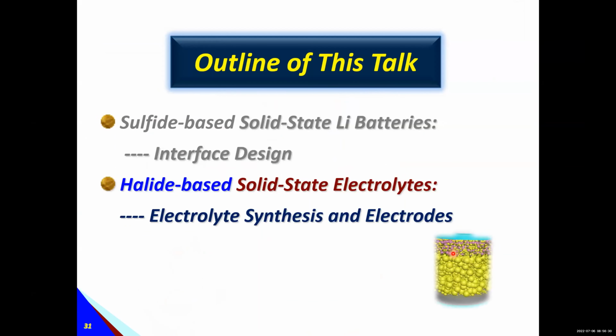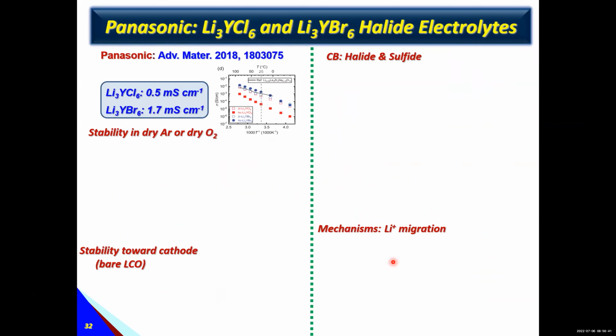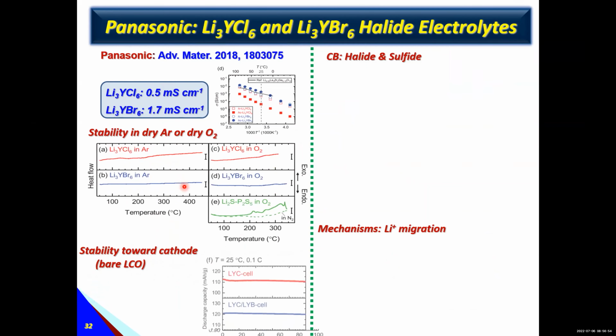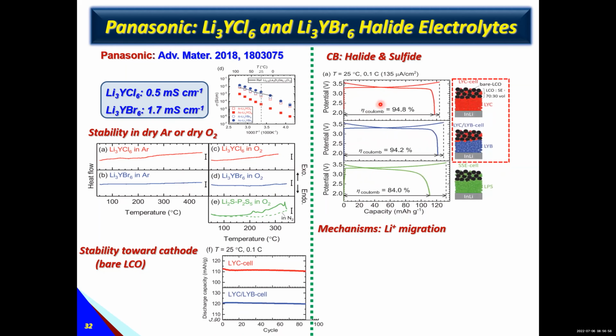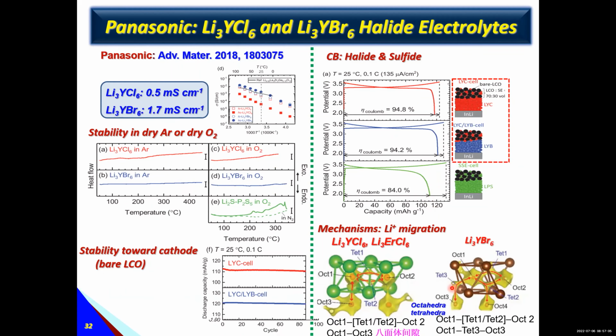Okay, so I finished the first part. Let me use maybe 10 minutes or less to finish this part. Halide-based electrolyte. Actually, we should thank Panasonic and the collaborators. They found the new system, lithium chloride, with very high ionic conductivity and also air stability. Without coating, they demonstrate its battery works, and particularly it's better than sulfide. So the structure has a lithium ion migration mechanism, particularly from octahedral to tetrahedral. That's why it has very high ionic conductivity.